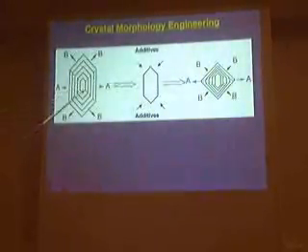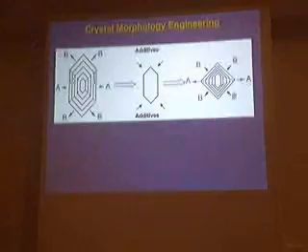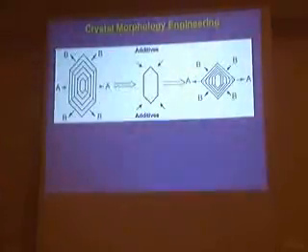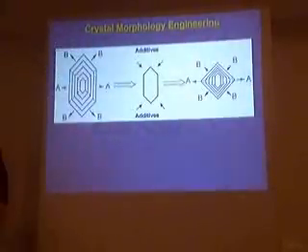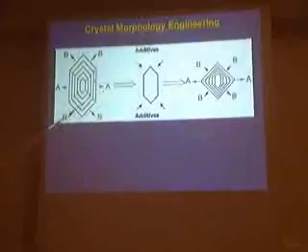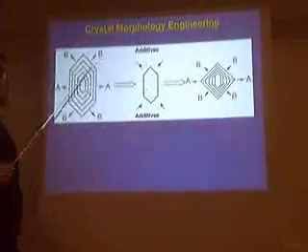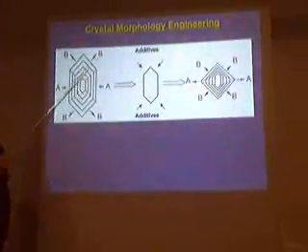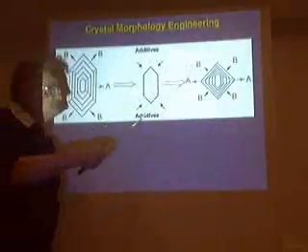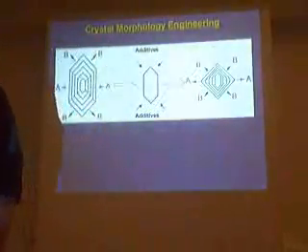And then the point is that if we are speaking now in terms of surface recognition for the molecules of the environment, we can believe that this dimer, which very much resembles that of the crystal structure, can be attached only to some specific surfaces of the crystal, and that by being attached to some specific surface of the crystal, it can change the morphology of the crystal. Because if you have a molecule which can be attached to this particular surface, and there is another group which perturbs the growth in this particular surface, the surfaces of the affected faces will increase now.